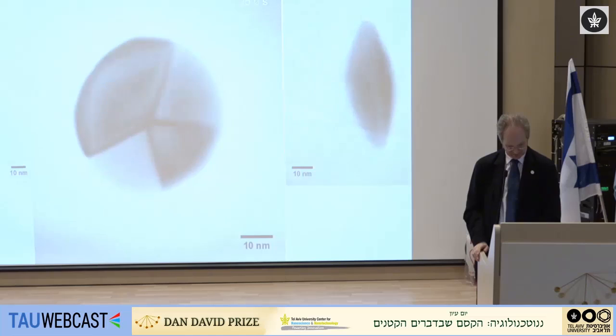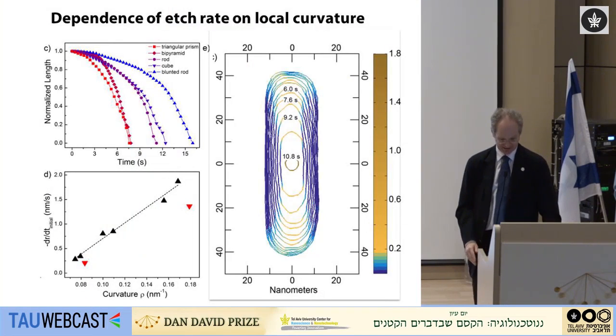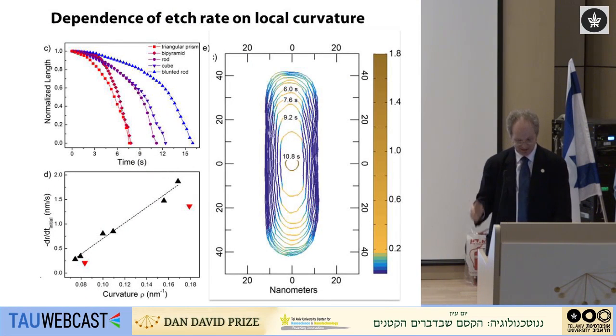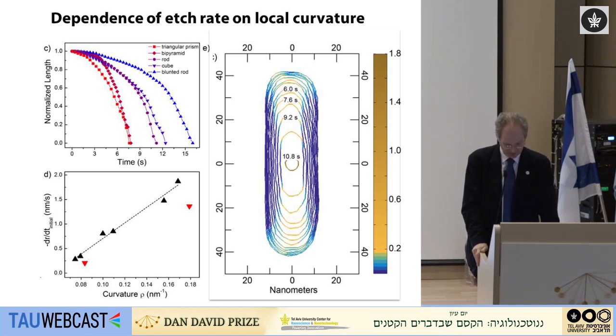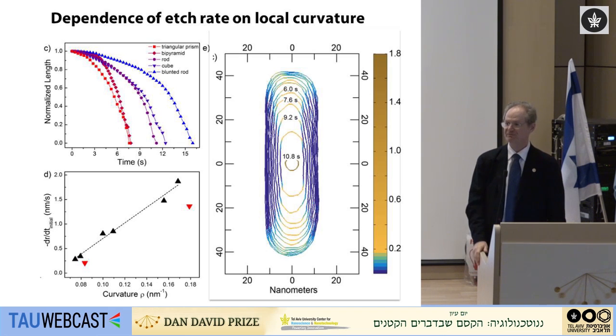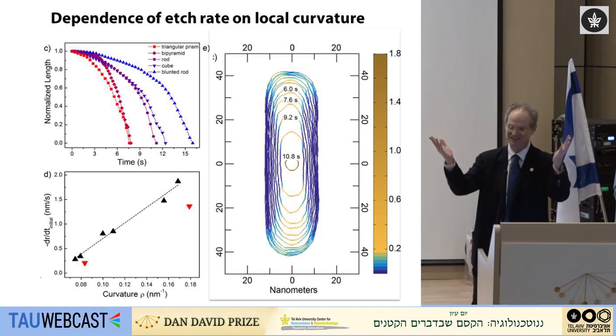Now, it turns out that we can convert this into real science. And the first thing that we can do is simply take these rods and make many of them and track how their dimensions change. So we can make a plot, and if we do that, what we find is that under all other conditions being fixed, the rate at which the crystals disappear is simply related to the curvature. The more the crystal's curved, the faster it's etched.